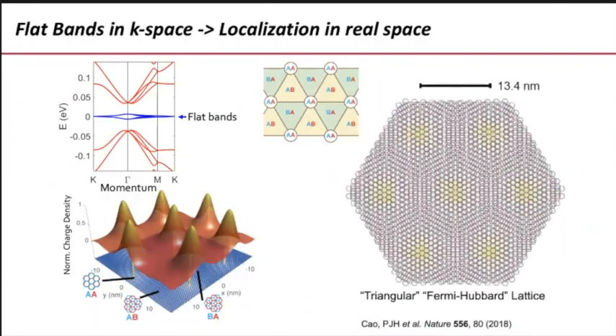In a slightly more realistic schematic, the real separation between these AA regions of the Moiré pattern, which I shaded here in yellow, is about 13 nanometers. And this is going to form the equivalent of a triangular Fermi-Hubbard lattice in cold atoms. Although there are many quotes here: first of all, it's not really triangular, it's a honeycomb, the AB and BA regions are not the same.